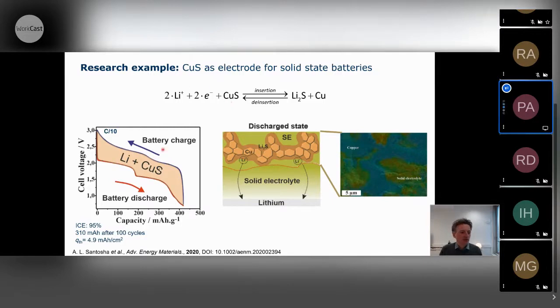battery. I also wrote here some specifications of our cells. We really try to always work with reasonable loadings. The electrode has a theoretical capacity of around 5 milliamp hours per square centimeter. And we also don't use too much solid electrolyte in our battery. We try to use just 30 weight% in the cathode, which is quite a reasonable value, I would say.